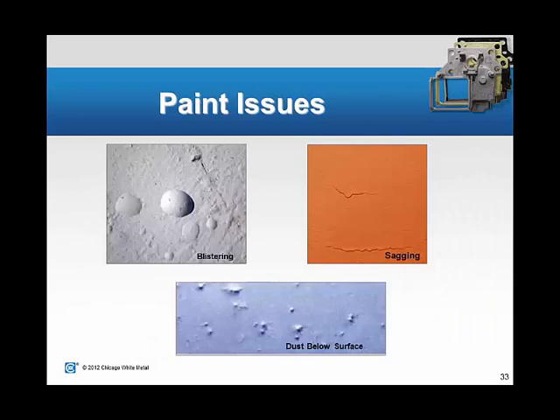A couple of the paint issues to look out for: blistering and dust below surface. Those are typically caused by improper cleanliness of the part prior to the paint being applied. So that's just something to keep in mind, and work with a house that knows what they're doing as far as surface preparation and getting the part ready to be painted. Sagging typically occurs because, again, too much paint is being applied, or the part is being racked in a certain way that you'll have some sagging, as we call it, of the paint.